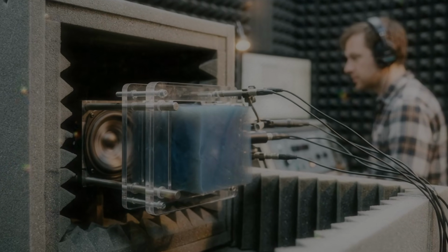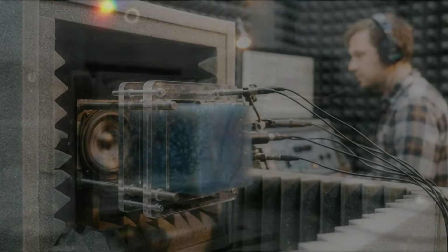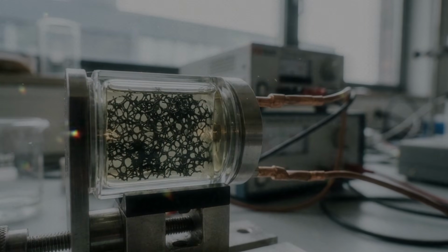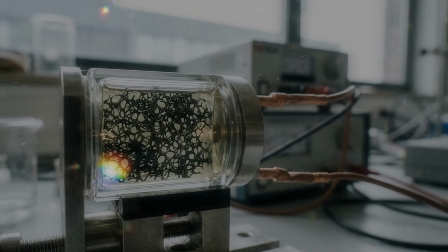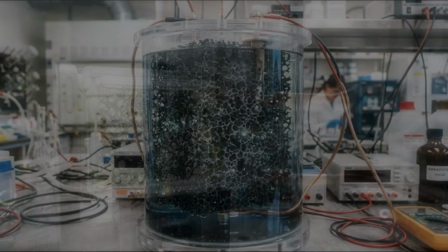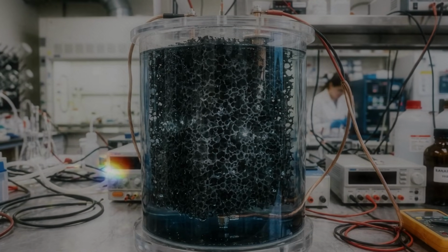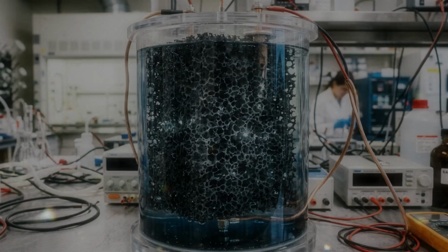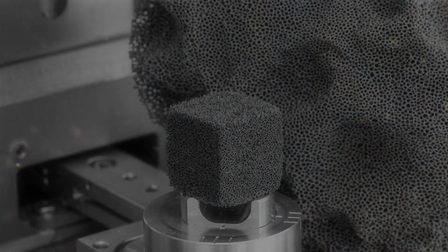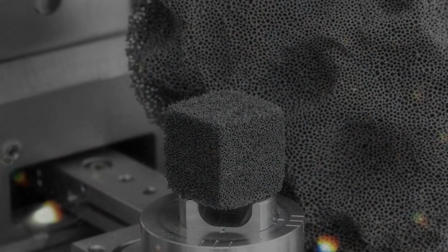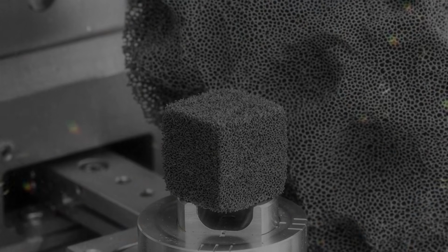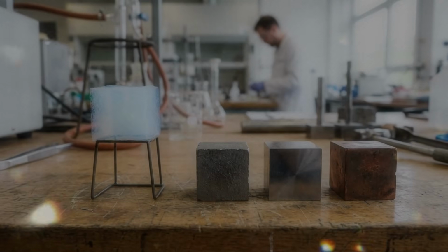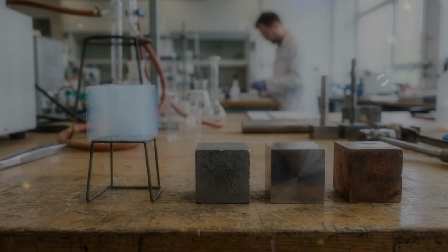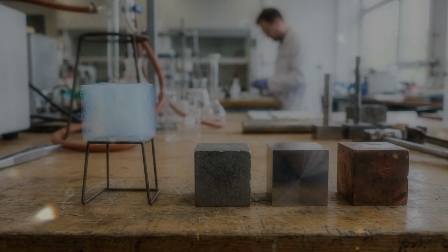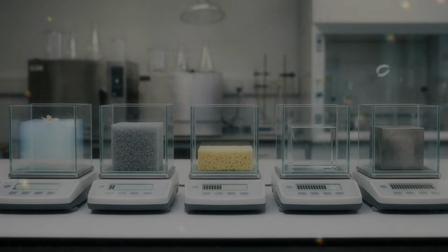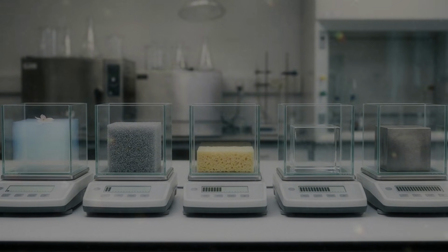Researchers can use this behavior to heat water, speed evaporation, or create sensors that respond to light. A floating layer of carbon aerogel can absorb sunlight while drawing water toward its warm surface. The surface water evaporates, leaving salts or other material behind. The idea sounds simple, but practical systems must control several problems. The aerogel has to remain stable in water. It must allow liquid to move through its pores. It must avoid becoming blocked by salt or contamination. It must survive repeated heating and drying.